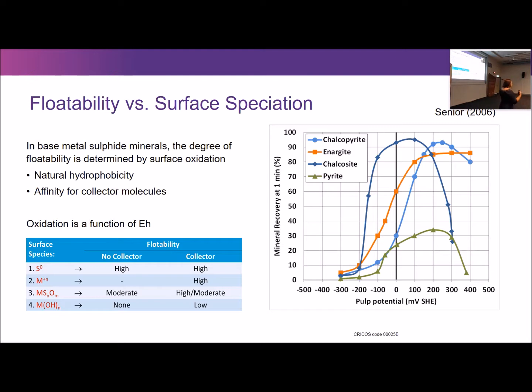As you continue to oxidize further, you start to form metal sulfoxy species on the surface. So you have a bit of oxygen being mixed in the system. Sulfoxy species are moderately water soluble, so when you have them on the surface, the hydrophobicity starts to drop off, they interact a bit more with water, but they interact beautifully with collectors. And so as a result, in the presence of collector, we have really high floatability here.